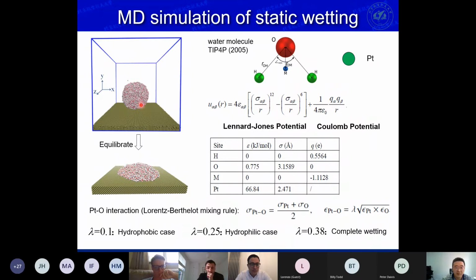And because we simulate droplets on platinum-like surfaces, we also need the potential function for platinum. We use Lennard-Jones potential as well. As for the interaction between water and platinum, we use Lennard-Jones potential as well, and we use the Lorentz-Berthelot mixing rule to adjust the parameters, particularly here for the energy. For the energy, here is a scaling factor lambda. We use this to adjust the wetting property. Specifically, if lambda is 0.1 it is a hydrophobic case, if it's 0.25 it is a hydrophilic case, and if it's larger, it's like completely wetting. So that's the potential function and the parameters we used for the simulation of water droplet and wetting problem.